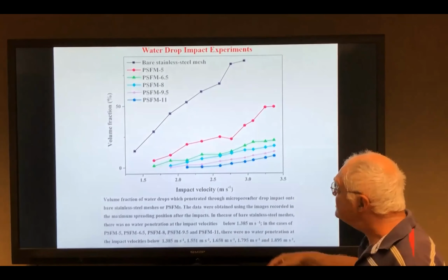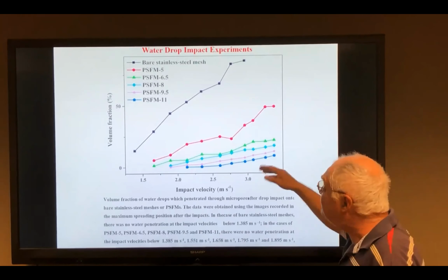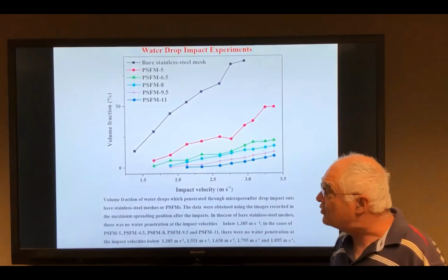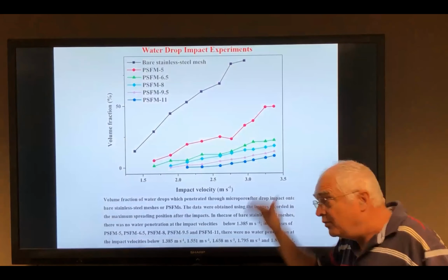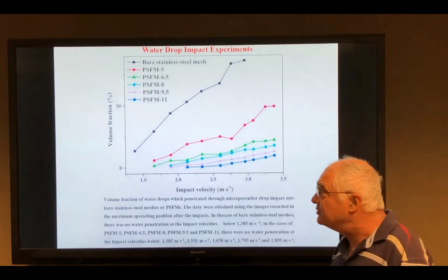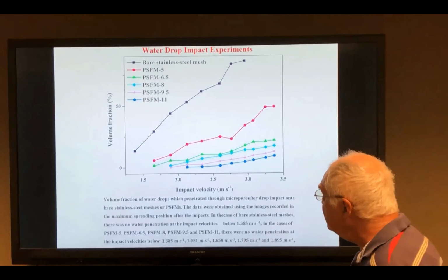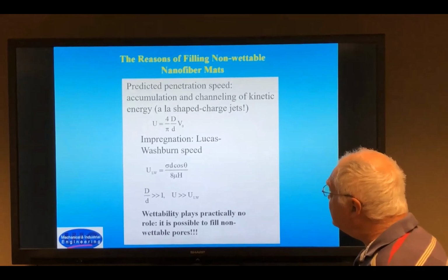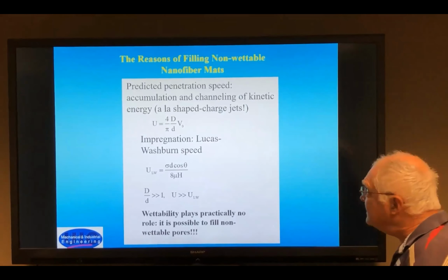Next slide, please. Here we demonstrate the volume fraction of water which goes through the membrane at different impact velocities. The higher the impact velocity, the more water goes through at a fixed thickness. So if you want to diminish this, you have to make a thicker membrane. Please go ahead.